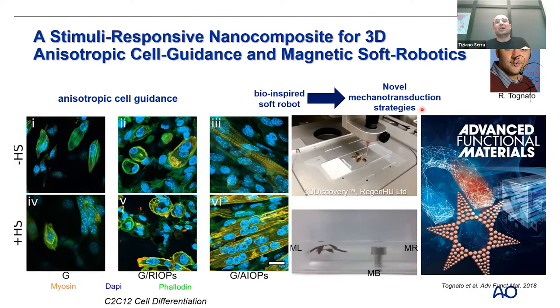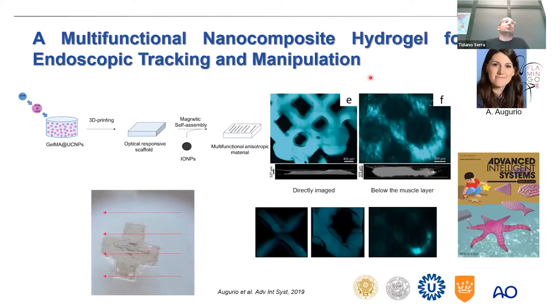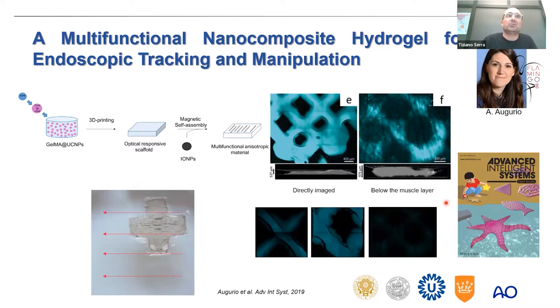Another opportunity is to use this soft hydrogel as a bio-inspired soft robot — for instance to let a jellyfish swim — but also to open the way to novel mechanotransduction strategies. You can create a hydrogel embedded with cells, implant it or place it in vitro, and then stimulate it remotely with cyclic magnetic fields to trigger cell differentiation. We also mixed this magnetic nanocomposite with upconverting nanoparticles to visualize the hydrogel even below the skin or a muscle layer, opening the way to endoscopic tracking and manipulation of novel medical devices.